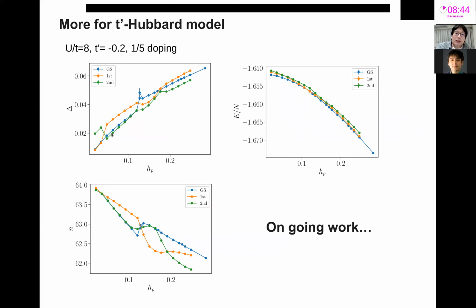And here we simulate not only the ground state, but also the first excited state and the second excited state from DMRG. They are not necessarily the true ground state or excited states, but at least there are three orthogonal states found by DMRG. And you find that there are several competing states with extremely close energy and with a similar superconducting order, but they have very different responses in the density when you apply a pairing field.